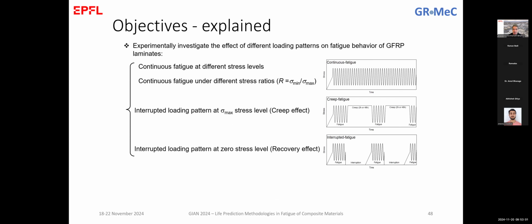So what we did, as mentioned, we did continuous fatigue until the end. Then we did interrupted fatigue loading at high stress, during the interruption keeping a high stress, which was exactly the same as the maximum stress of the cyclic loading. There we kept two different interruption times to simulate creep, 2 hours or 2 days. And we also did interrupted fatigue where, during the testing, we were interrupting the constant amplitude fatigue loading and going down to 0, so unloading the specimen completely.